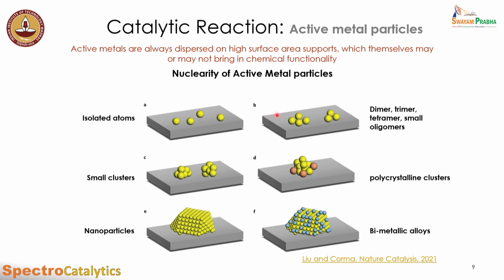They are still formed on the XY plane. They haven't gone to the Z plane. But if we still increase the loading, now we are going in the third dimension, and here we are forming small clusters. What is the difference between this and this? Here all the atoms are interacting strongly with the support, whereas some of the atoms here are not so strongly bound to the support, and hence the sites which are bound to the support have a different electronic configuration than the sites which are not in direct contact with the support.